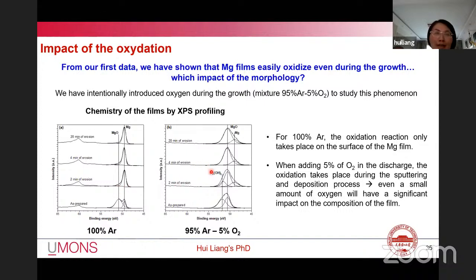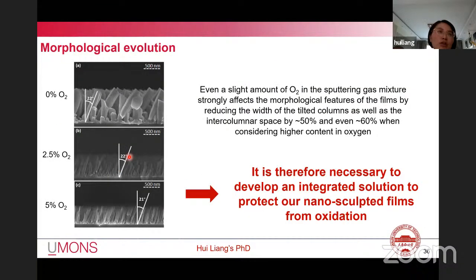And refer to the second figure. When the amount of oxygen is increased to 5%, the oxidation takes place during the sputtering and the deposition process to obtain the MgO film. Even just a small amount of oxygen will have a significant impact on the composition of the film.